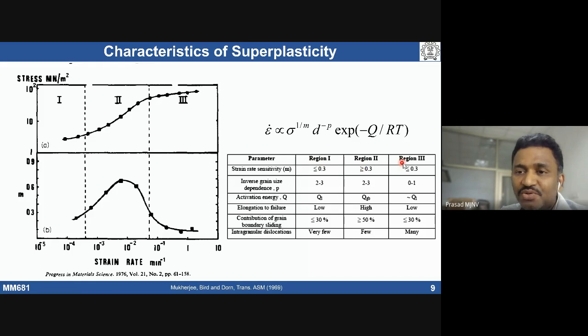Okay. So the region 1, region 2, region 3, if I see typical strain rate sensitivity values, m is less than 0.3 for region 1. Similarly, region 3 also less than 0.3. But region 2 will be having anywhere between 0.3 to 1. Inverse grain size dependence.